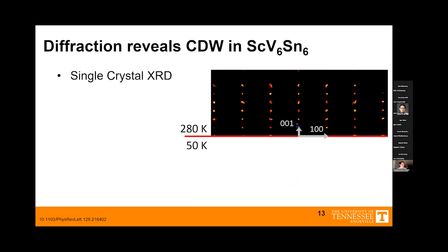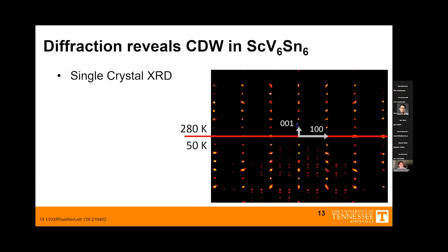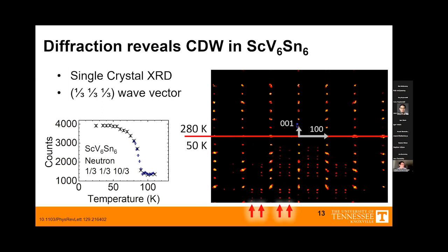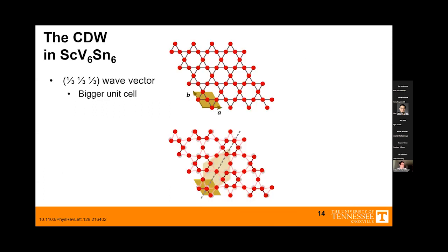So, single crystal X-ray diffraction. At room temperature, we see our nice rectangular array of peaks. And at low temperatures, we see this new charge density wave develop with a 1/3, 1/3, 1/3 wave vector. You can see these new rows of peaks appearing. This 1/3, 1/3, 1/3 has been quite a lot of fun. It turns out that's not what DFT would initially predict until you start really digging into the details. We also have neutron diffraction confirming that this really does develop at the transition observed in transport and thermodynamic properties.